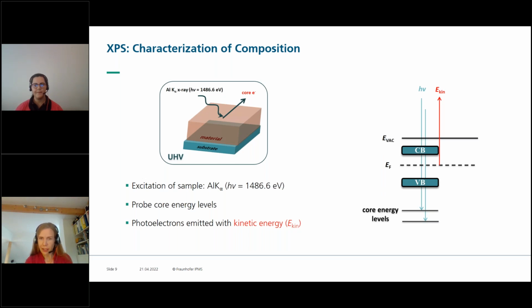Another question for you, Jenny, from Finland. What is the XPS spot size, and can it be used as a line scanner? Yes. For aluminum Kα X-ray sources, we can go down to 7.5 micrometers, and we can go all the way up to 200 micrometers. So it's really helpful when you look at structured samples. And we can definitely do point analysis, and we can also do line analysis. So you can measure multiple points across one line, and you can also do area analysis, so close to mapping, let's say. So these are the possibilities.